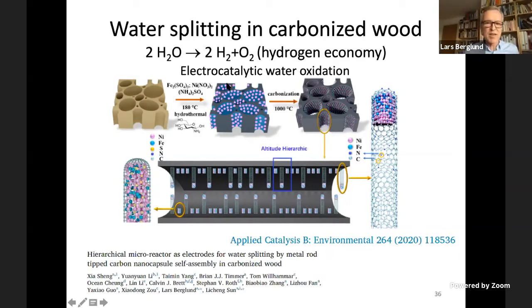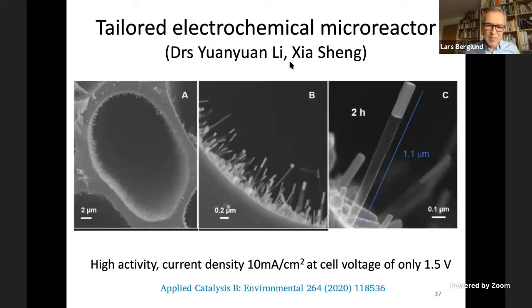So basically, you want to split water. And if this is successful on a large scale, that could contribute to the hydrogen economy. So it's electrocatalytic water oxidation. And this is basically what the structure looks like. So they managed to create these thin carbon nanotubes, which have catalytic particles on the surface.